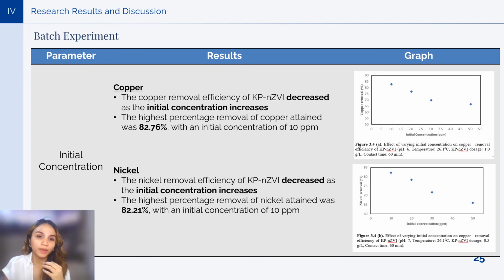The next process parameter is initial concentration. For copper, the removal efficiency of KP-nZVI decreases as the initial concentration increases. The highest percentage removal for copper is 82.76% at 10 ppm. For nickel, the removal efficiency also decreases as the initial concentration increases, while the highest percentage removal for nickel was attained at 82.21% with an initial concentration of 10 milligrams per liter.